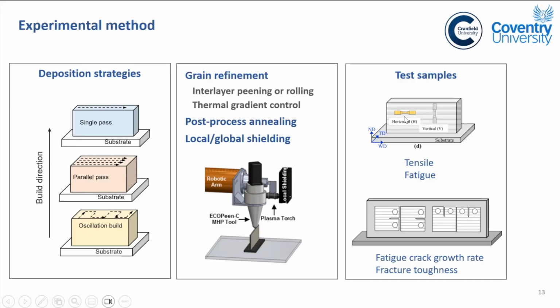Then we extract these dog bone samples, either in the build direction or horizontal to the build direction, for tensile and fatigue S-N curves. But we are also working on fracture mechanics properties. We use compact tension specimens for fatigue crack growth rate, and also measure fracture toughness for cracks either parallel to the layers or transverse to the layers.